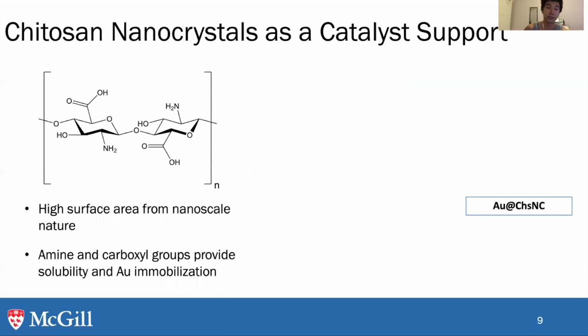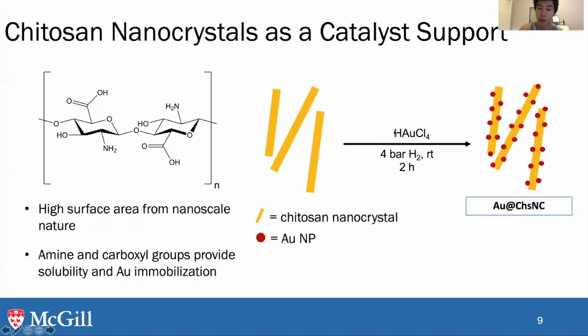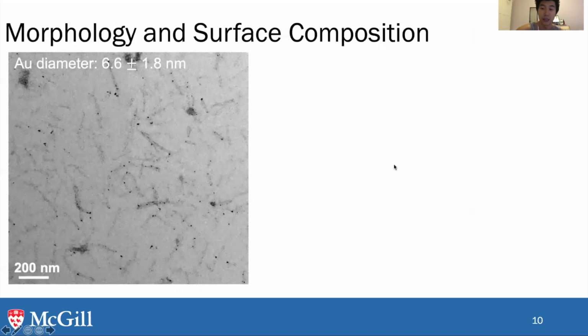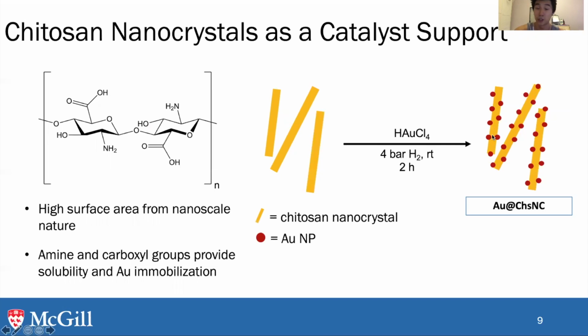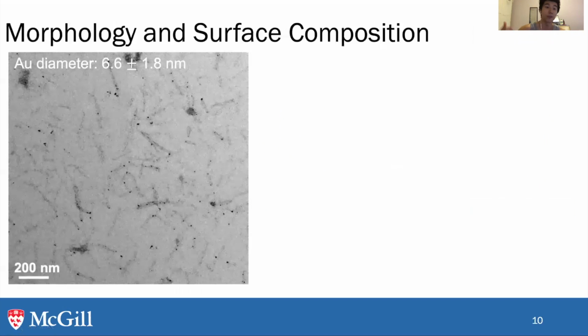So now we have a characterized chitosan nanocrystal and fully confirmed. We really want to use this now as a catalyst support. Due to the high surface area from the nanoscale nature, as well as the amine and carboxyl functionalities being used to stabilize a metal nanoparticle catalyst, we used a gold precursor and hydrogen reduction to put gold nanoparticles onto the nanocrystal itself. So it's a very benign procedure. And from the TEM, you can see here, we confirm that we have gold nanoparticles embedded onto the chitosan nanocrystal itself with relatively small polydispersity.